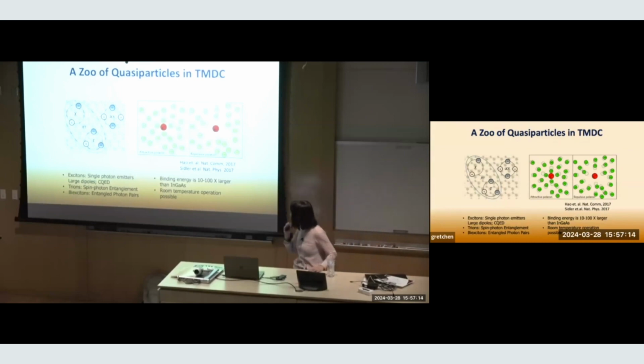But in these monolayers, because they're so thin, the Coulomb field that binds the electron hole pair actually permeates outside the layer, which enhances the binding energy to something like 200 to 400 meV. So it's a quasi-particle that is stable at room temperature. You cannot ignore them anymore, so you have to deal with them. And this is an exciton, a bound electron hole pair. Here's a trion, basically an exciton bound with an extra charge, either electron or hole. Strangely, they're energetically more stable than an exciton. This trion transition appears at lower energy than the exciton transition. You can also have what's called a biexciton, two excitons bound together, and they're also energetically stable.